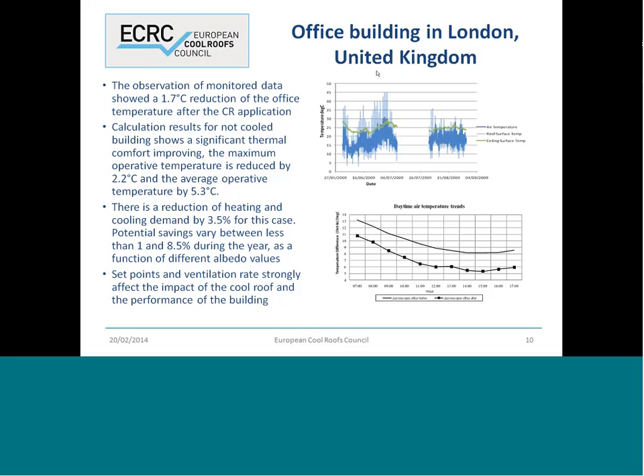The calculation for the active cooling configuration shows a reduction of 3.5% of the global energy demand, which means heating plus cooling. And according to a parametric analysis, potential savings vary between 1 and 8.5% during the year as a function of different parameters. Albedo value is one of these parameters, but the performance also depends on the system set points and the ventilation rates, which strongly affect the impact of the cool roof and the performance of the building.